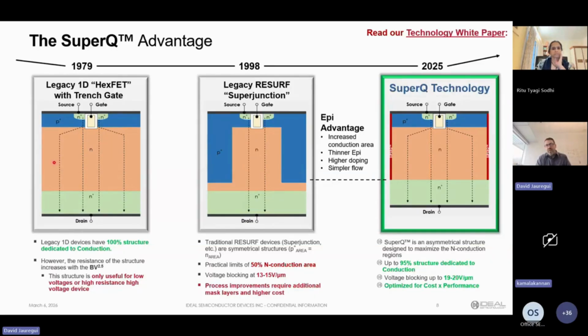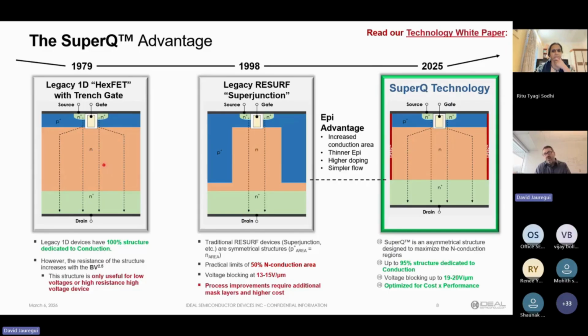And at that point, you're really following geometric features of the epitaxial, meaning that the thinner and the higher doped the material, the lower the on resistance. It just follows those basic fundamentals like any resistance material follows. The issue with this structure is that when it came to leveraging this material to block voltage, as you increase the voltage, the on resistance of this material, or the resistivity of the material, had to increase at a 2.5 exponent rate, meaning that if you have a 100-volt device and you went to 400 volts, the on resistance is going to increase by more than 4x.